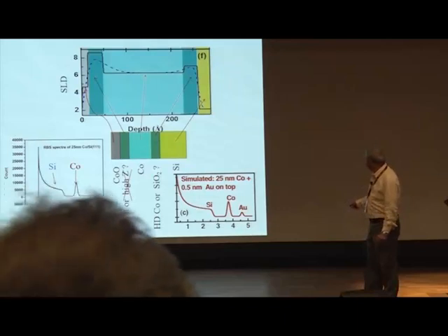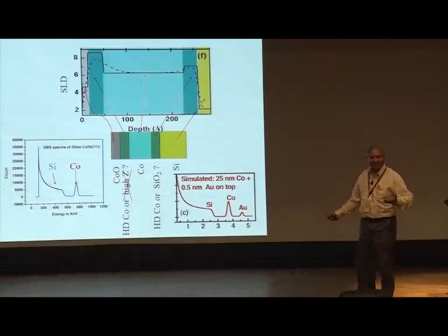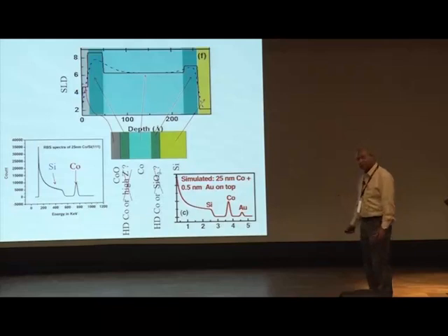Similarly, at the interface, you have a possibility of forming silicon dioxide, but silicon dioxide has a much lower density even compared to silicon. So that is also ruled out. So these two layers are definitely high density cobalt layers.